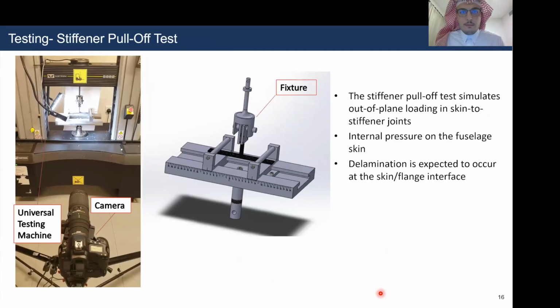After the T-joints have been manufactured, they were mechanically tested through what is known as a stiffener pull-off test. In the stiffener pull-off test, a universal testing machine has been utilized, which simulated tension. And then a camera was used to take images of the in situ damage analysis.